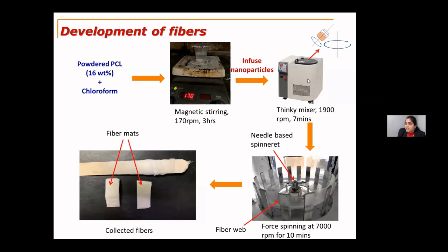So once we mix the nanoparticles with the polymer solution, this polymer solution is infused into the spinneret. Approximately 2 to 3 ml of solution will go into this spinneret.